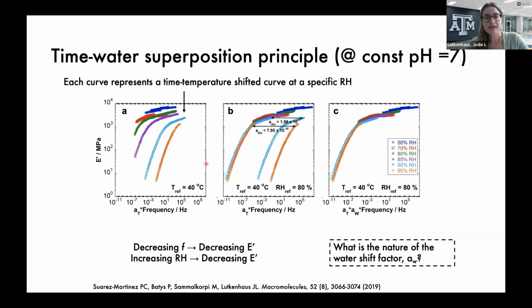Now, what we do on the next slide is we measure the storage and loss modulus, but we're just showing you the storage modulus here at different humidities. So now we have all these time temperature shifted curves, but taken at different relative humidities, okay? Because water is going to change the relaxation. We perform a horizontal shift, and we have to add in a second shift factor depending on water. And with that shift, you can see there's reasonable overlay of the data.